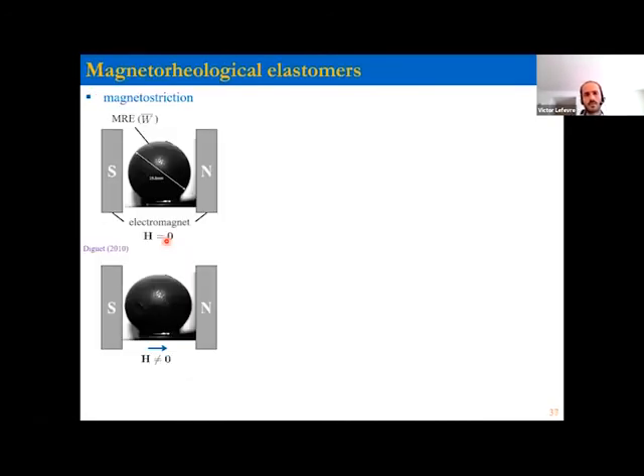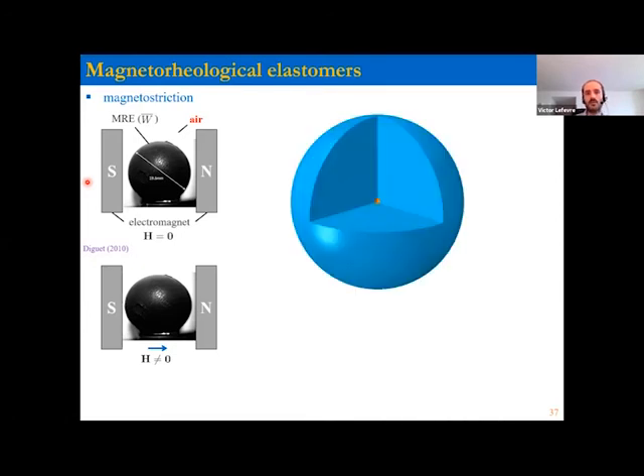So again, that's a typical setup that people use to probe the response of MREs. They make a specimen, in this case, that's a sphere. They put in the magnet, an electromagnet, they switch the current on, and they measure how much that deforms. There's an important catch with this setup. It's the fact that the whole thing happens in the air. And in the air, as you know, you can have magnetic fields. And so you need to account for the air and the magnetic fields that are in the air, where you're going to look at the response of these specimens. That's what we did. Numerically, this is just a big sphere of air surrounding our spherical specimen of the MRE.